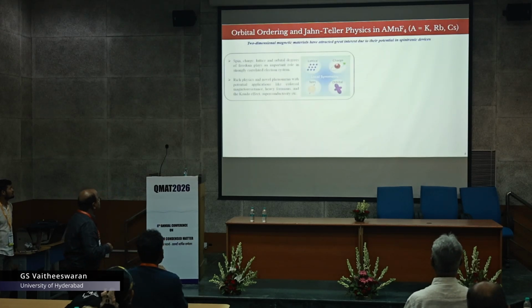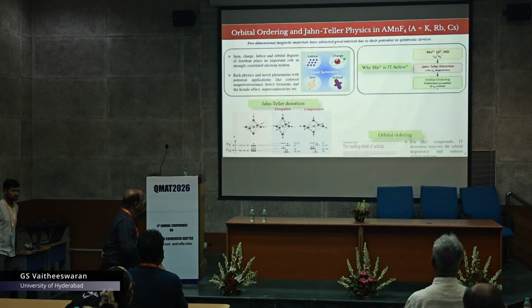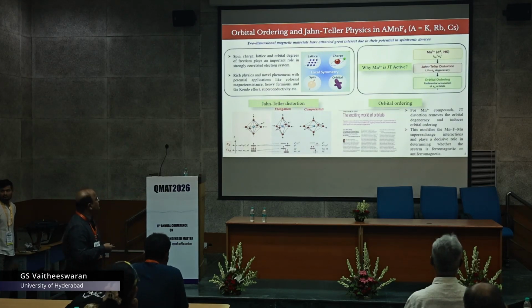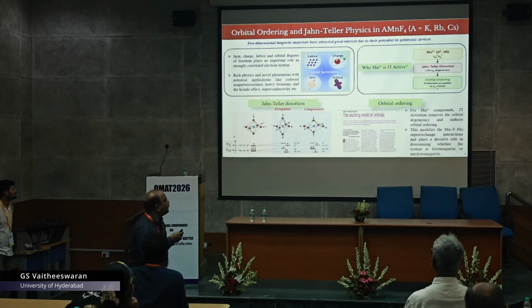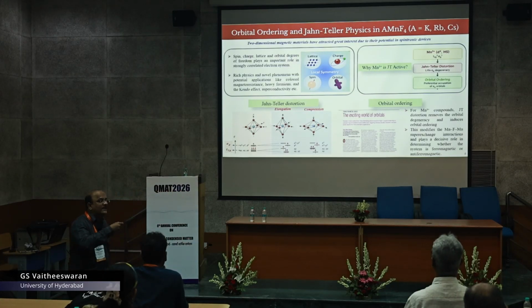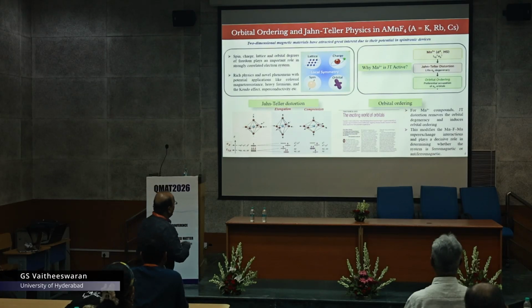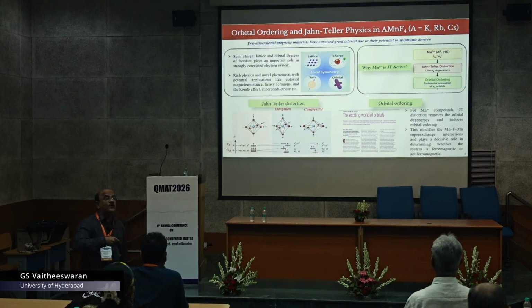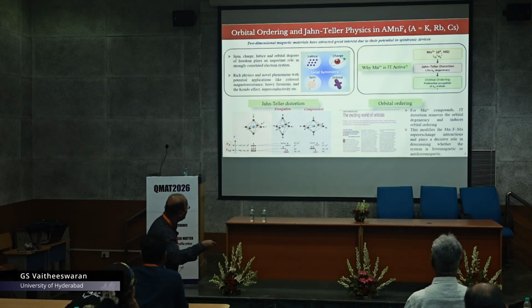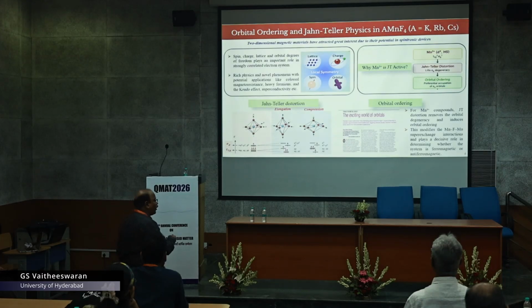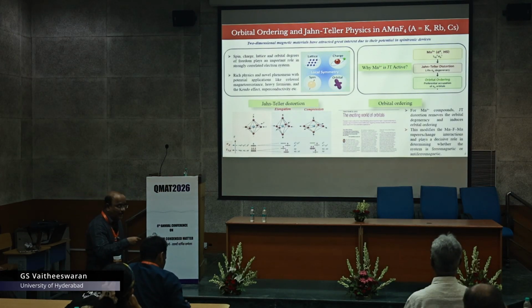As we talk about transition metal oxides, orbital ordering is one of the famous, popularly known phenomena, which depends upon how the d orbitals are occupied with the t2g and eg, and eventually it will lead to several kinds of distortion. The prototype is an orthorhombic system, where we have a distortion, and this leads to interesting orbital physics, and then we see orbital ordering, which can coexist with magnetism. There is an elongation or compression depending upon the Jahn-Teller effect, and this is so popular in manganese systems. Here manganese is 3+, which is highly Jahn-Teller active.